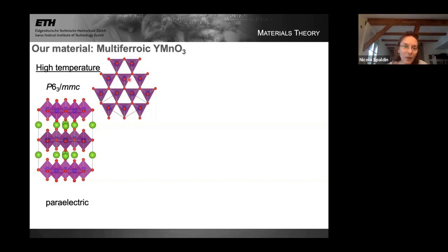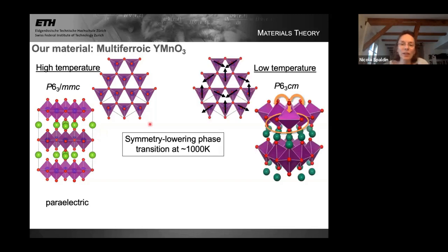Okay, so this is the crystal structure at high temperature. It's paraelectric. There's no spontaneous electric dipole. It has a center of inversion. The spontaneous symmetry lowering phase transition happens at around 1000 Kelvin. And two things happen at this temperature.